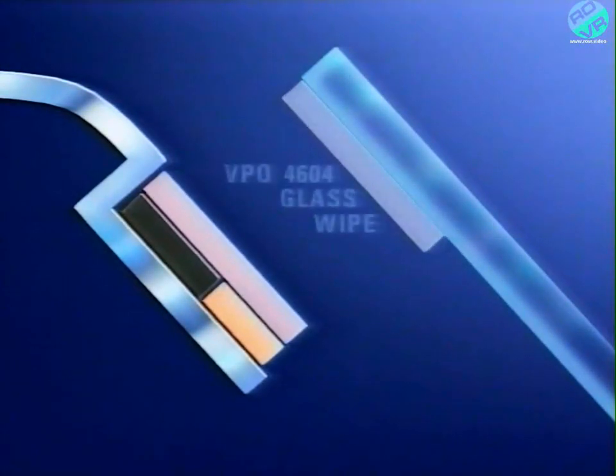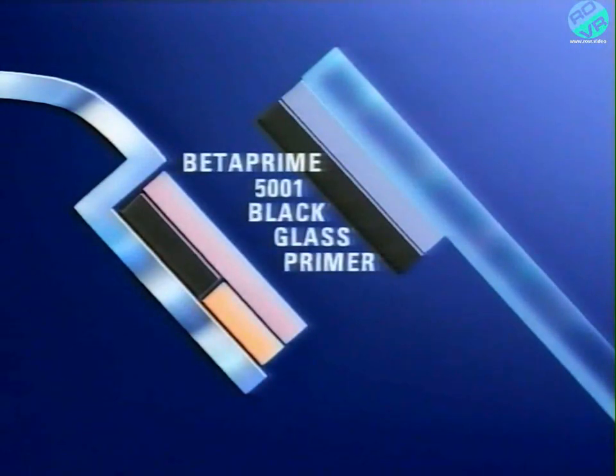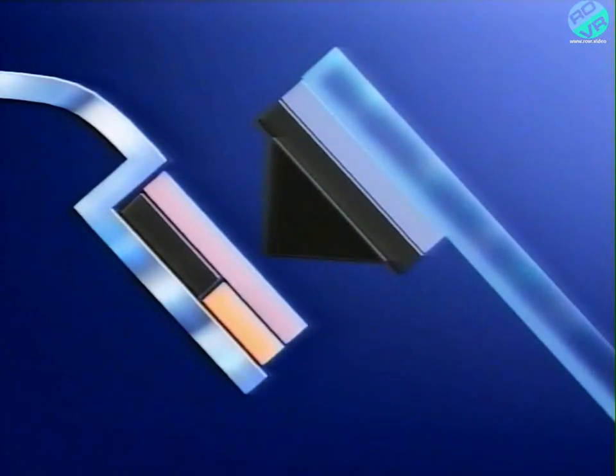VPO 4604 glass wipe is applied to prepare and etch the surface of the glass. Betaprime 5001 black glass primer is wiped onto the edge of the glass to provide ultraviolet protection. Betamate E2400 polyurethane is now extruded onto the edge of the glass. Finally, the glass is pressed into the pre-prepared aperture.